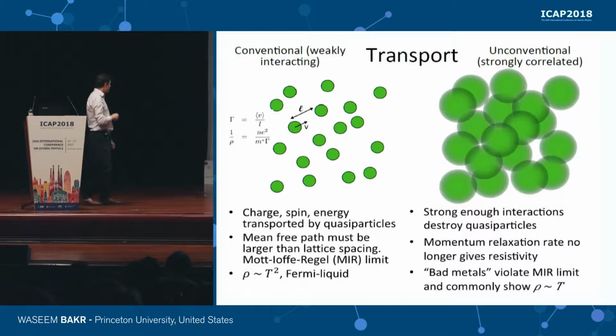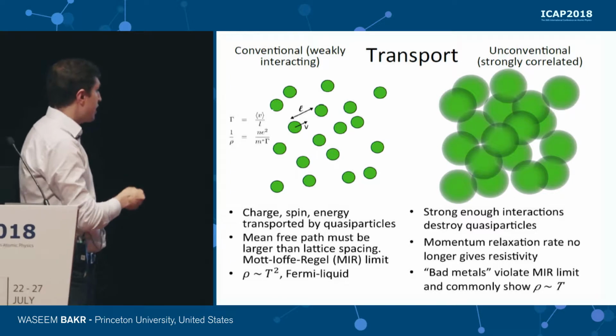OK, so if we now start to heat up a system, and we assume the only scattering is due to interactions, then we find that the resistivity, as predicted by the Boltzmann equation, would go like T squared, the temperature squared. Eventually, it would saturate at a bound that we can infer from this MIR limit. Of course, mean free path is something difficult to measure in a condensed matter system. So usually, experimentalists measure resistivity, and they can use that bound to put a maximum possible resistivity that you can measure. So that's the situation in a weakly interacting system.